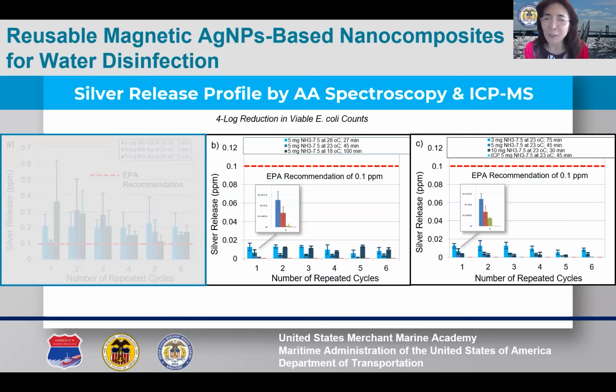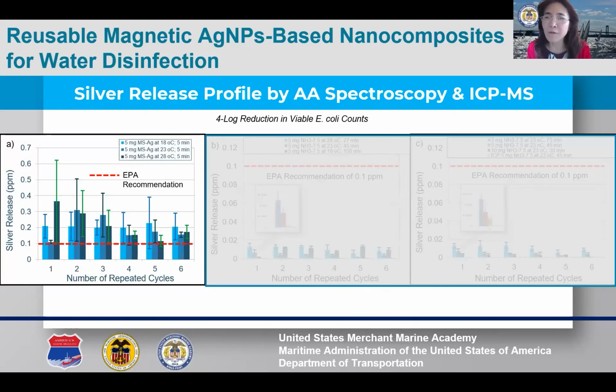levels remained remarkably constant and very low, at levels below 0.015 ppm, regardless of disinfectant amounts and varying temperatures. These values, confirmed by ICP mass spectrometry, were significantly lower than the EPA's 0.1 ppm recommendation. In contrast, as shown in figure A, all MS-Ag samples showed silver releases above the 0.1 ppm EPA recommendation level.